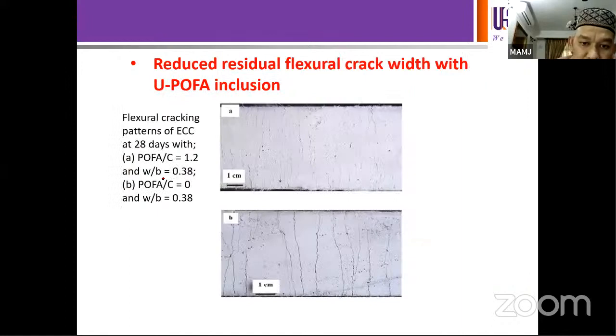All right, you can see the same scenario. The case of A is the one with POFA over cement of 1.2, and in the case of B is the one without having POFA at the same water binder ratio. So A is having finer cracks and a much bigger amount of finer cracks, while B is having bigger cracks with a smaller amount of cracks.